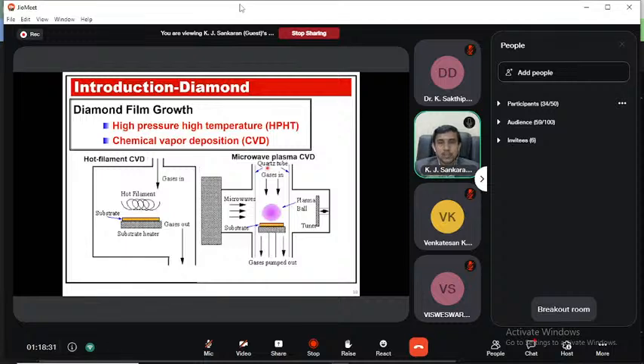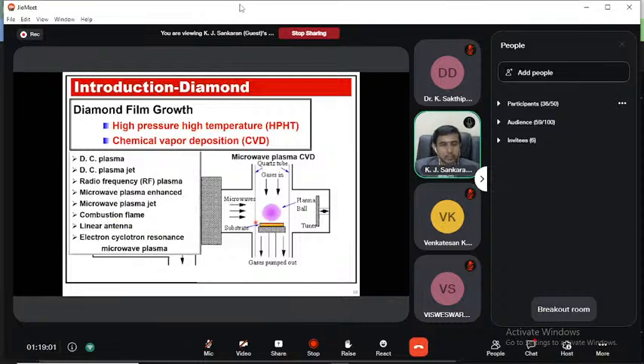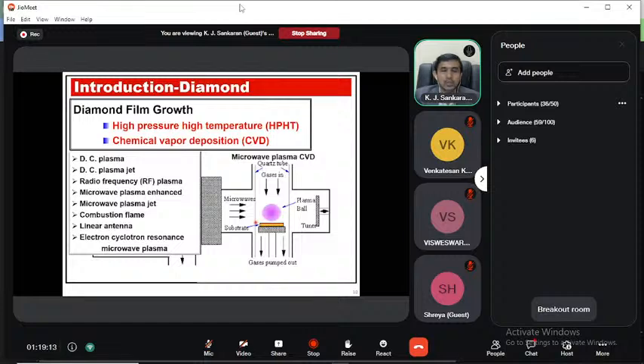The gases are let into the chamber, then the microwave reacts with the gases and dissociates them with its high frequency of 2.45 gigahertz. So the ionization of the gases creates the plasma. Then the plasma contains carbon species which are converted into sp3 hybridized carbon that can be coated as a thin film on the substrate. So this is artificial diamond preparation using the chemical vapor deposition process. There are various microwave plasma CVD processes like the DC plasma jet and RF plasma. Based on the different sources, CVD follows with plasma-based growth of diamond.